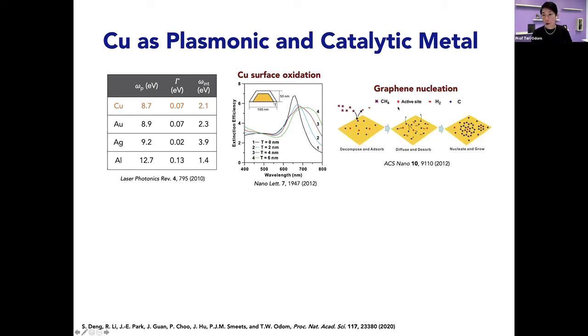And so there's literature precedent on using chemical vapor deposition with methane as a source and hydrogen as part of the reductant. And part of the reason we wanted to grow graphene is, well, we wanted to see whether we could conformally coat the particles, but also it would mitigate this effect related to copper surface oxidation. Because once the copper comes out of the chamber, it immediately forms an oxide and is not self-limiting. It's more similar to silver in this way, and the quality of the resonance is compromised.